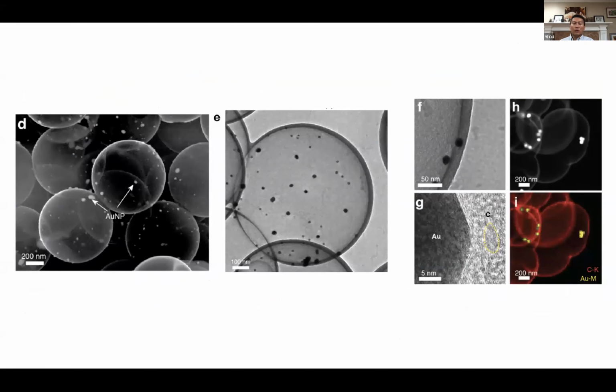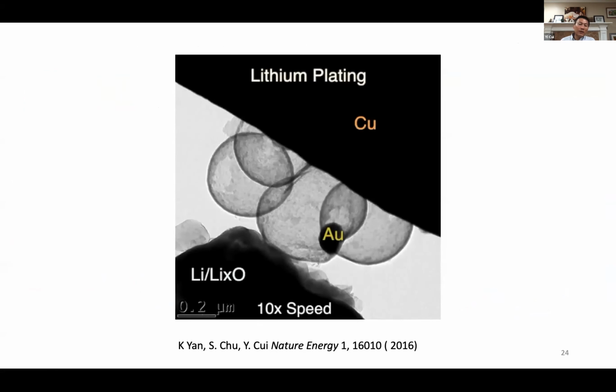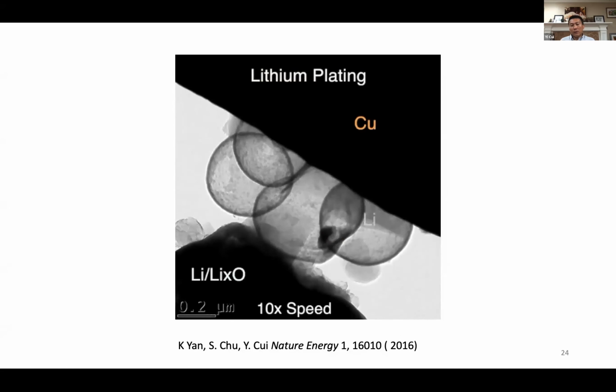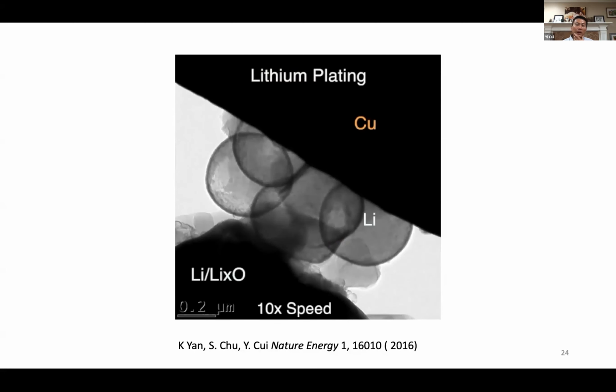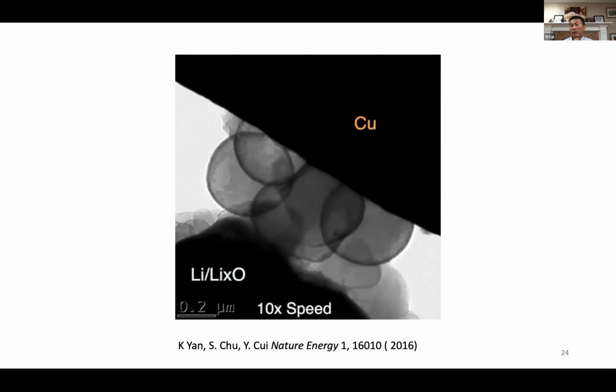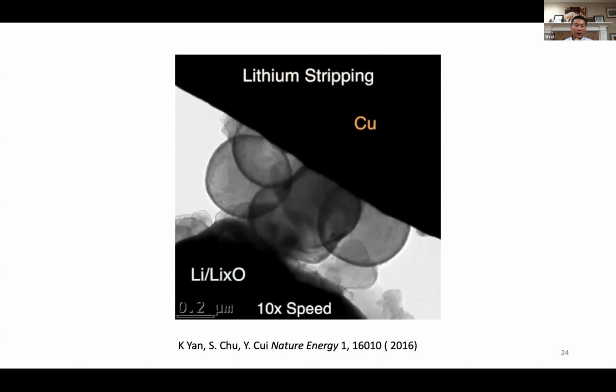So we made this structure with a gold seed particle inside this hollow carbon sphere, on the order of about 800 nanometers in diameter. Using in-situ TEM, again, the tool is very important, we were able to observe lithium coming in, plating in this dry in-situ battery cell. You see the gold nanoparticle in the middle. Lithium metal comes in and dissolves gold away. And then once you strip lithium away, this gold nanoparticle will come back. You'll see it in a few seconds.